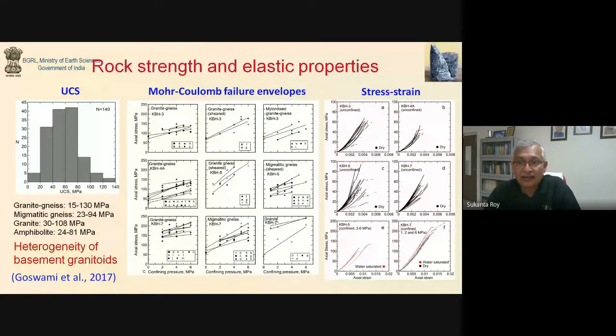We also carried out rock strength and elastic properties measurements using the facilities available in the country. We actually carried out these experiments at CSIR CIMFR in Dhanbad. And we measured the strength of the rocks under unconfined as well as confined conditions, and stress strain relationships. You can see that the UCS measurements here show a large range in the values for the different rock types, which means that the basement granitoids in Koyna region are essentially very heterogeneous in terms of rock strength property.